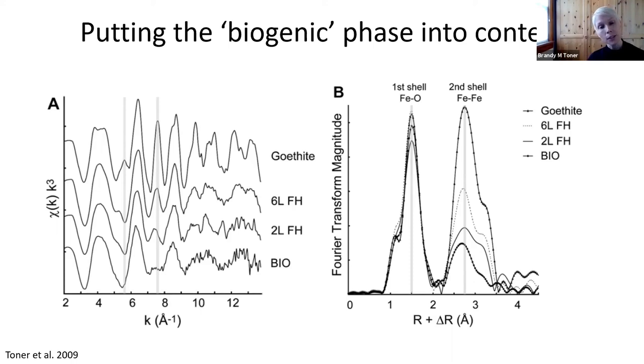So on the left-hand side, you're looking at the goethite spectrum on the top and this biogenic signature on the bottom with six-line and two-line ferrihydrite standards in between. And then on the right panel, you're looking at the Fourier transform, of course, showing the iron-oxygen interatomic distances in the first shell. And goethite here creates that tall second shell.